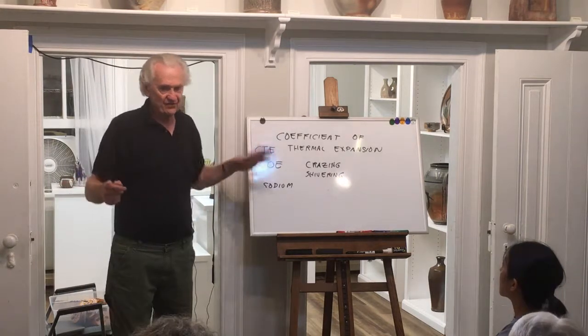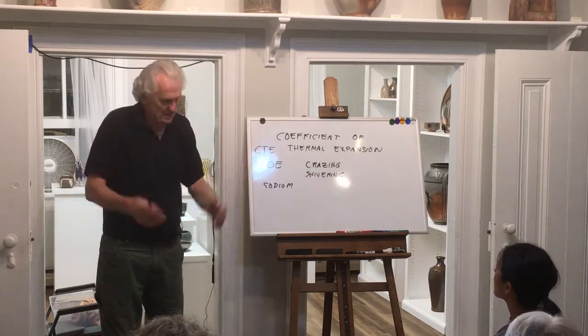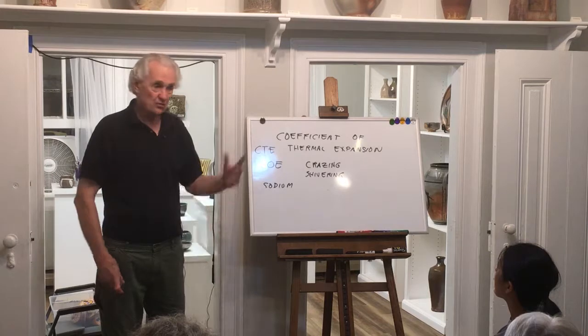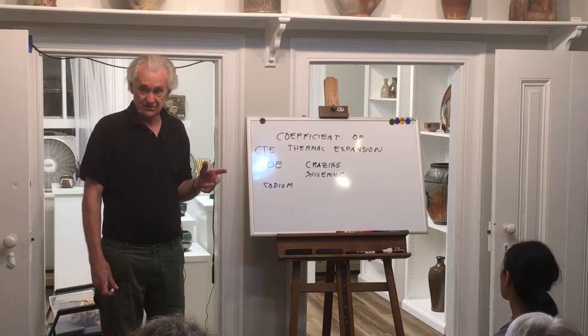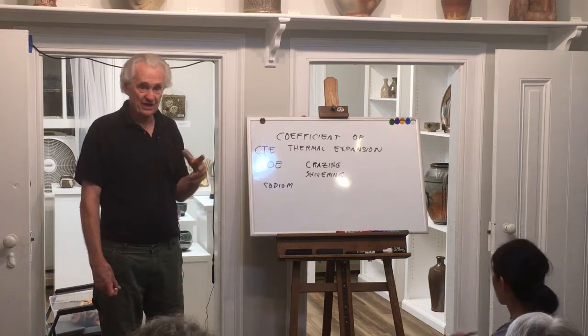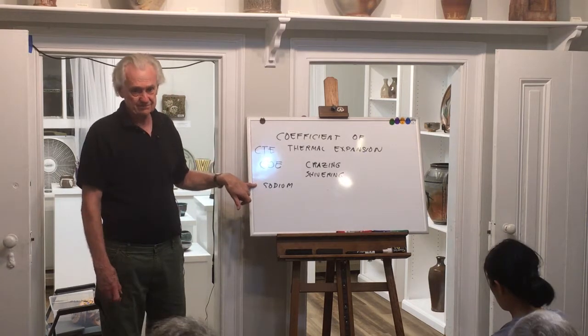Because a lot of sodium gives it a high coefficient of expansion, and when that glaze cools, it shrinks like crazy, and it's going to craze. Which is why, for instance, carbon trap glazes, carbon trap shinos that have soda ash, craze, because they have a lot of sodium in them.